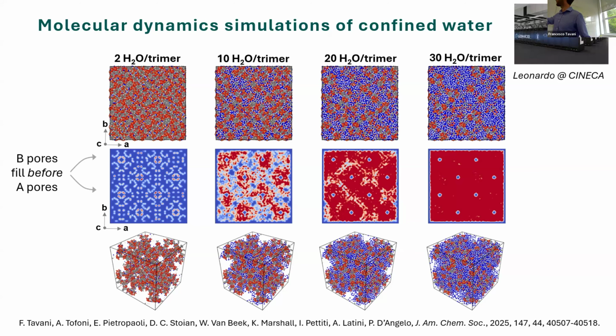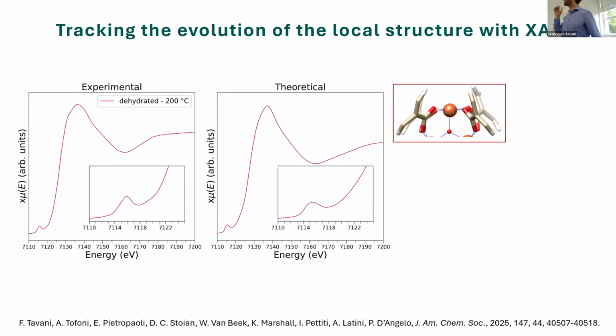Let me add that we did the same simulations up to 40 water molecules per trimer. I don't have the image here, but this is not the highest loading we explored. And what is happening to the local structure from a theoretical perspective? This is a simulation of the experimental iron K-edge XANES. This is the first 100 eV, more or less, region on the left.